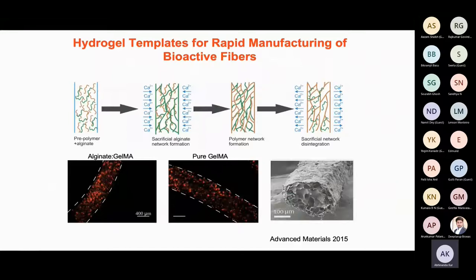So just to show you how this universal bioink that I mentioned works, basically the idea is to be able to sequentially cross-link two different types of polymers so that the same kind of approaches that are used very regularly for printing alginates can be used to print virtually any type of material. So in this case, as you know, there are a lot of approaches based on extrusion and coaxial extrusion of alginate and calcium-rich solution that is used to print alginate-based materials. Now, if you mix the alginate with different types of polymers, like polymers that are photocrosslinkable, then you can print the alginate structure, then use light to cross-link the secondary structure, and then get rid of the alginate by solutions like EDTA, etc. So you're left only with the secondary material.